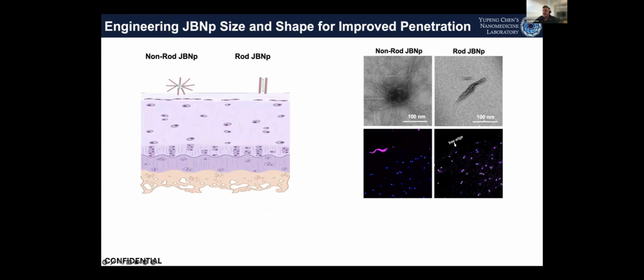And when we take a practical look at the difference in delivery between a non-rod shaped and a rod shaped JBNP, which we can achieve by changing the ratios of components and the sonication power, it's clear that the non-rod shaped JBNP cannot penetrate the cartilage deeply, while the rod shaped JBNP can due to its slim profile. We demonstrated this directly as seen on the right in cross sections of cartilage, where non-rod JBNPs aggregate on the edge of the cartilage, but rod-shaped JBNPs are able to penetrate the cartilage and deliver to the cells.